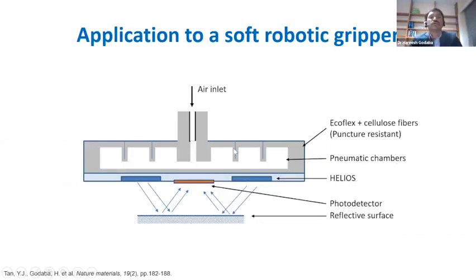Yeah, so we've taken this electroluminescent device and tried to apply this to develop an application in soft robotic devices. So what we did is we basically tried to make a proximity sensing capability by utilizing this stretchable light source. So what we did is we took these stretchable light sources and embedded them in a pneumatic gripper, which is basically a gripper made of stretchable material.